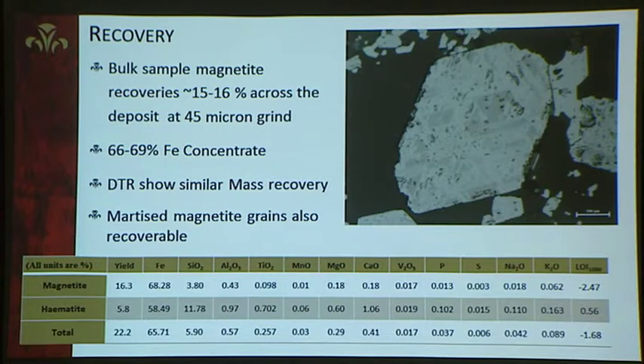Across the deposit, we're finding our magnetite recoveries coming in at around the 15 to 16% mark on average, and that's at a 45 micron grind. And with that, we're getting 66 to around 69% iron concentrate, and we do have examples that go over that as well, at around 70. We're also finding that DTR is showing similar figures to global mass recoveries.